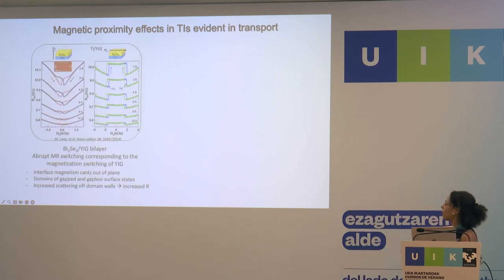Magnetic proximity effects have been seen before in transport. Here again, we're not talking about making a device. We're just putting a bilayer on and measuring the resistance and seeing what features appear, to try to characterize this proximity better. Here's an experiment that came out some time ago of just bismuth selenide on a magnetic insulator, YIG. What you see here are little switching dips as a function of a perpendicular field, and then hysteretic peaks as a function of in-plane field.